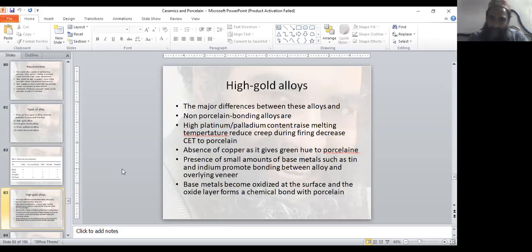Now, high gold alloy. Major differences between these alloys and non-porcelain bonding alloys are high platinum palladium content, which raises melting temperature, reduces creep during firing, and decreases CET to porcelain. Absence of copper, as it gives green hue to porcelain. Presence of small amounts of base metal such as tin, because it relies usually for bonding on tin oxide, not copper oxide. And indium promotes bonding between alloy and overlying veneer. Base metal becomes oxidized at the surface and the oxide layer forms a chemical bond with porcelain.